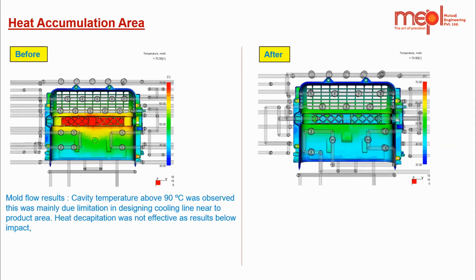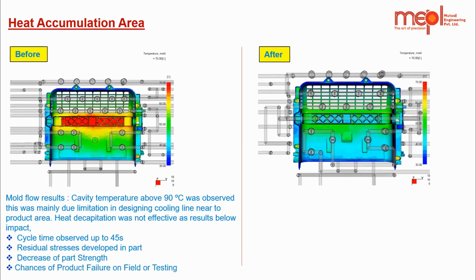In this part, we had heat accumulation, due to which the cavity temperature was going very high, above 90 degrees. Because of limitations in the design of the cooling area, the heat dissipation was not so effective. Due to this, we observed the cycle time going high.